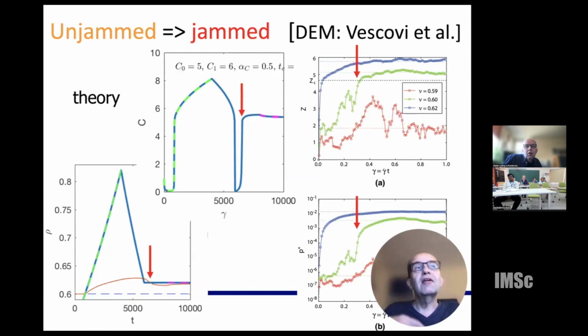Now, there is a special case, and that is when you have an unjammed system and you shear and the system jams, as was presented by particle simulations by Vescovi et al. a few years ago. And we made the theory for this, which gives density and coordination number and pressure, all the continuum quantities. The red arrow indicates the jamming event. So there is a possibility that you have an unjammed system, you shear and you jam the system. In simulations, it's the green line. In theory, it's the blue line with the marker.